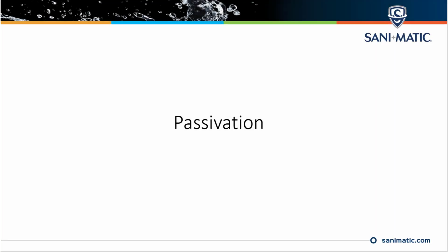Passivation. I think one of the biggest misnomers people have is that they think passivation is a chemical process. Chemicals work to allow the metal to passivate, but stainless naturally creates its own passive layer in the presence of oxygen if it's allowed to be exposed to oxygen. Typically, you want at least 24 hours of oxygen exposure. I even recommend 48 hours, but it needs to be dry and clean and free of any sort of debris or oils or water, anything that would keep oxygen from contacting that stainless surface.